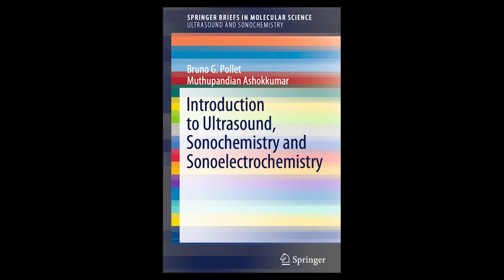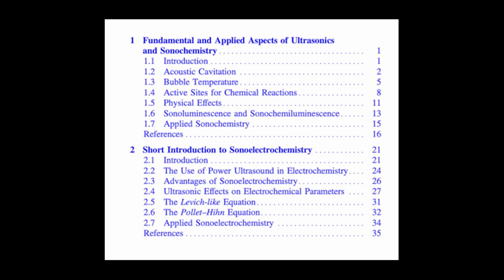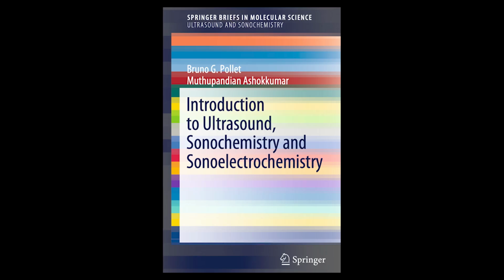Their chemistry depends entirely on those primary radicals that are generated in zone 1, manage to survive recombination in zone 2, and successfully diffuse all the way out into the bulk liquid before they react with something else. So only the hardiest radicals make it out there? Pretty much. Since the bulk solution is cold, the reactions happening here are typically driven by these highly energetic escape radicals initiating chemistry at room temperature.